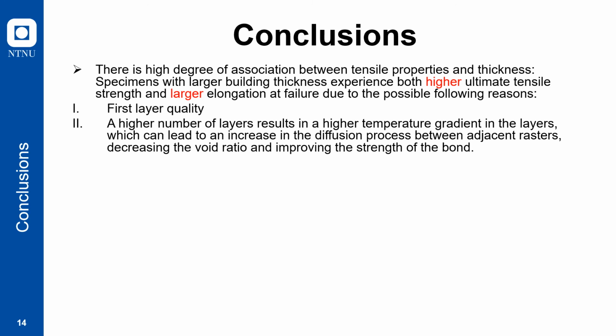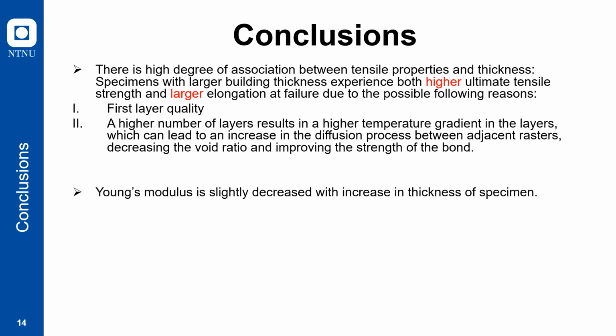And next, a higher number of layers can result in a higher temperature gradient in the layers, which can also lead to an increase in the diffusion process between adjacent layers. And this will result in decreasing the void ratio and improving the strength of the bond, which will improve the ultimate tensile strength as the thickness increases. And second, as you can see from the table I showed earlier, Young's modulus slightly decreases with the increase of the thickness.